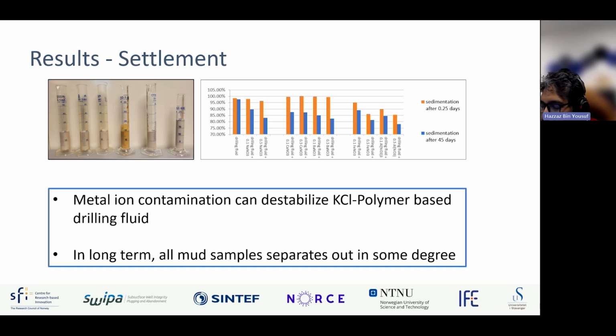So we found in our first research that iron is the reason why the sag barite formation is happening. So we wanted to test the effect of not only iron but all the metal ions, to see if metal ions themselves have this effect or not, and how metal ions affect the standard drilling fluid. And we found some really fascinating results. We found that the trivalent metal ions, which are both iron and aluminum, destabilize drilling fluid very quickly, in a very small amount. It destabilizes within minutes if we use some kind of iron salt or aluminum salt.